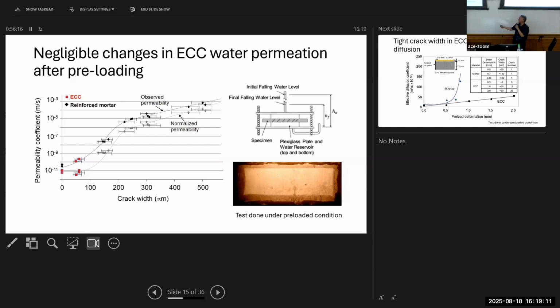For normal concrete, you are typically operating in this range, and you will let water get through very, very fast. But for ECC, because of the self-controlled tight crack width, water permeation is very slow, and that means that it will take a long time for water to get to where the rebars are, even if you have the rebars inside. So it will take a long time to travel through the concrete cover.